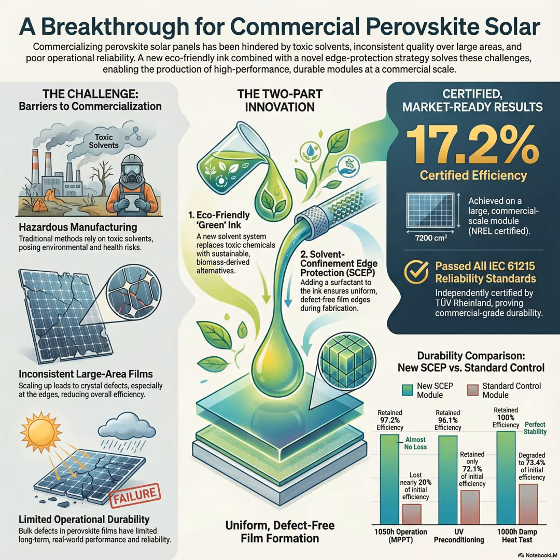The biggest problem is what they call voids. We're talking literal air bubbles and defects right where the perovskite meets the substrate. If you look at an old film under a microscope, it's just riddled with these tiny cracks. And those defects kill efficiency and let in moisture, which destroys the panel over time.